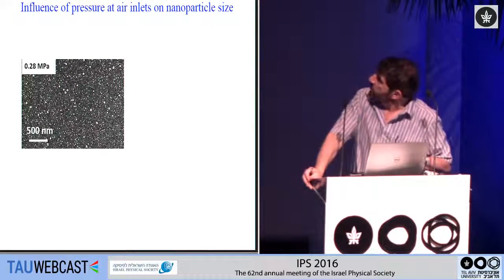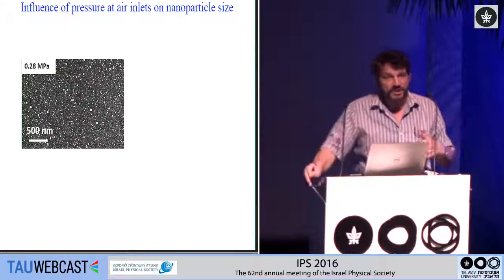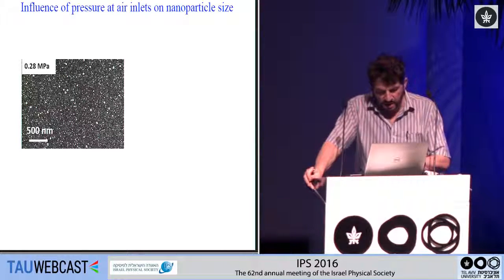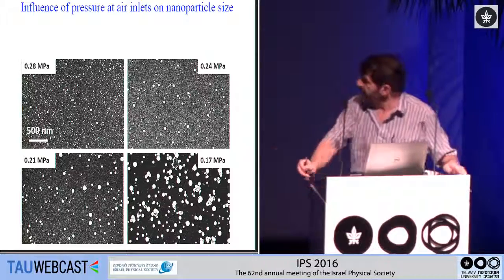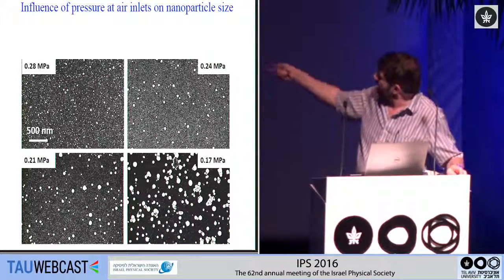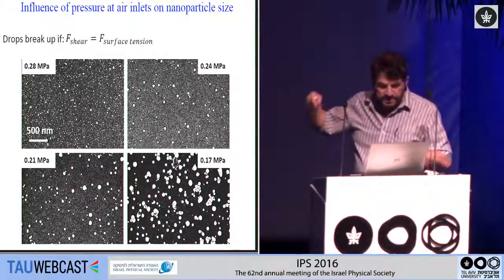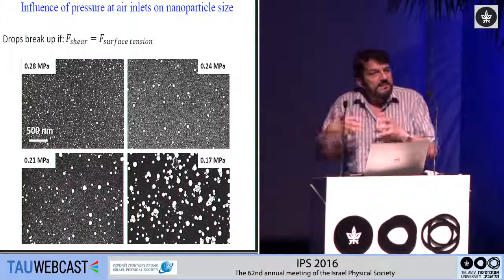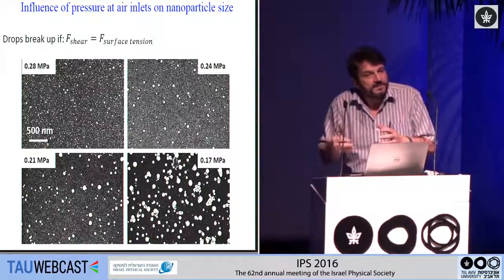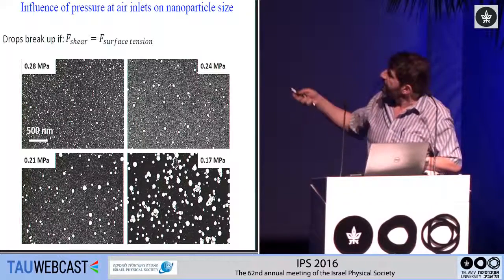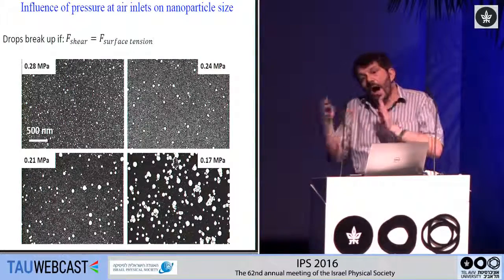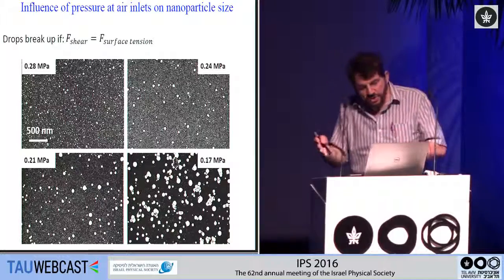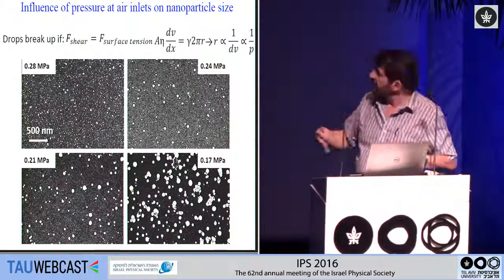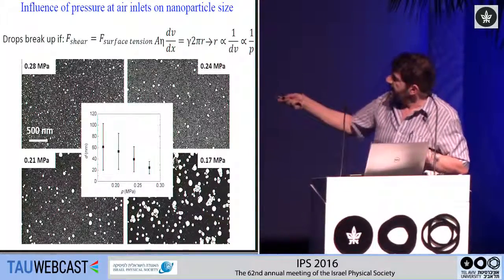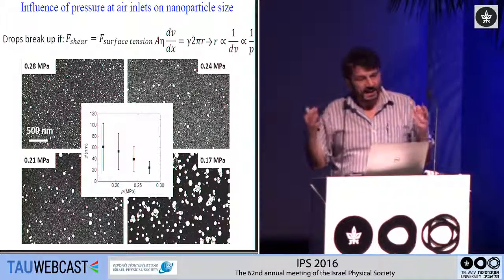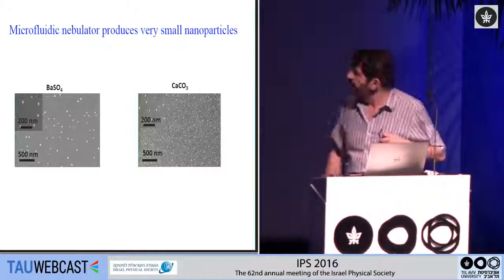And you can do this. You can vary the pressure that you use to feed the air, and you see that as the pressure goes down, the size of the particles goes up. That means the secondary drops that you're forming go up, and you can plot this. I'm changing the shear, you can calculate the change in shear, therefore the change in the size of the drops, and you get exactly what you would expect. It exactly behaves the way you would expect.